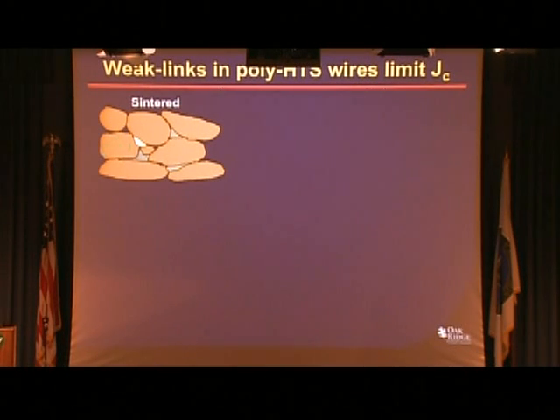So how do we make long lengths of wires of these superconducting materials so we can meet all these applications? As I mentioned to you, these materials are like ceramics. In other words, they're like the mud that you have in your flower bed, which, if you were to look under a microscope, would look something like this. You've got these grains, and you're trying to now combine this into a wire which is flexible and carries large amounts of current. And as you can imagine, these areas which are non-superconducting and these interfaces that are present can't really be too good for current transmission.